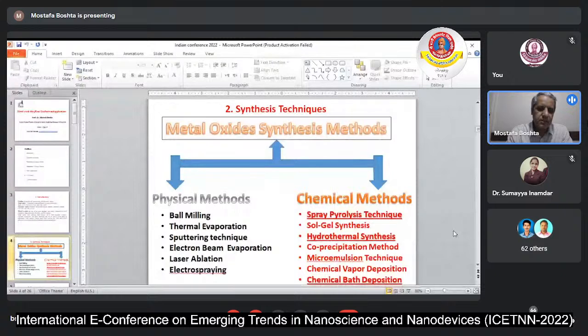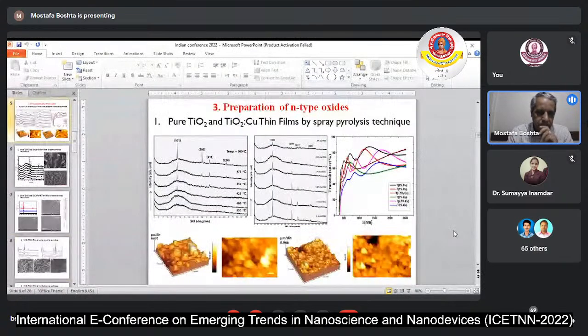Hydrothermal, everybody knows, is also a simple chemical technique. You only put the material in a Teflon bottle and close it and put it in the oven for a long time, maybe 1 day or 2 days, and after that you can get a thin layer or powder material. Chemical bath deposition is a simple technique to set up, and you can use it in each lab, and it is easy to work with. So I have prepared different materials.